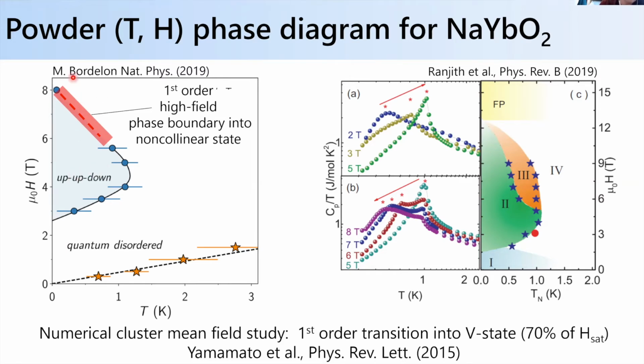We have some other data that I haven't shown you here because I don't want to go too much into the details, but suggesting that this upper field phase boundary is actually first order, a first order phase boundary into a non-collinear state. And this is consistent with some parallel NMR measurements that have been done, where they also seem to see a change in the upper field phase boundary between what they call state 2 and state 3 here. And it's also consistent with some expectations from numerical cluster mean field studies, where there are predictions that at this upper field boundary, you can have a transition into what they call this V state, right? Where the up-up-down state destabilizes, but it's not completely disordered. Okay.